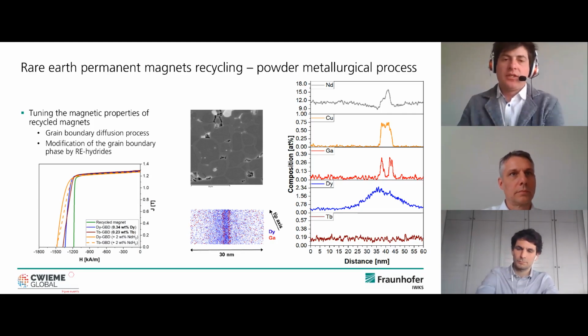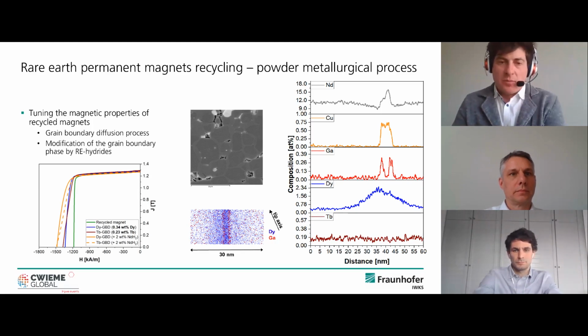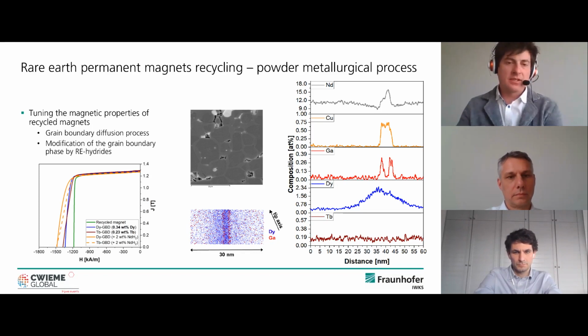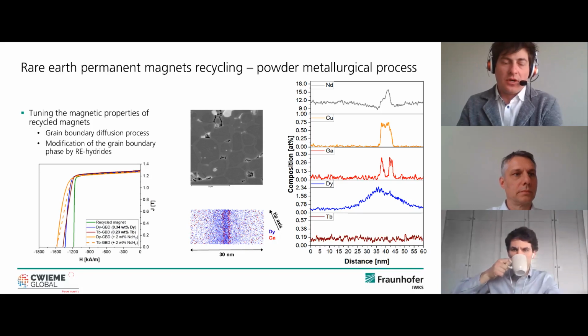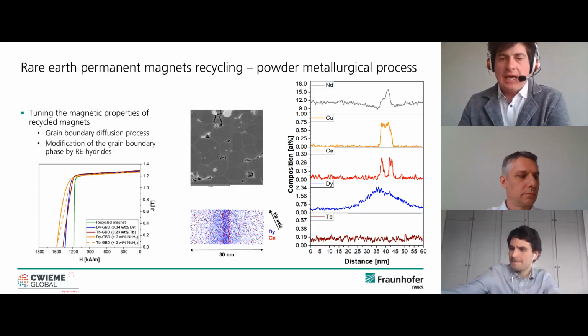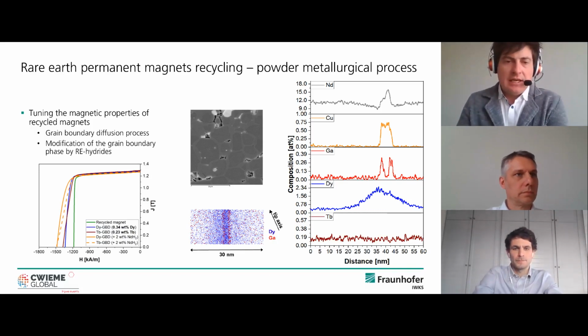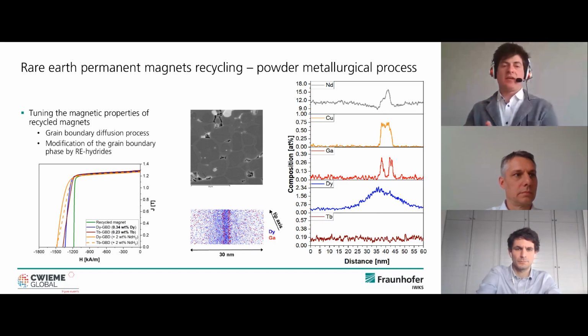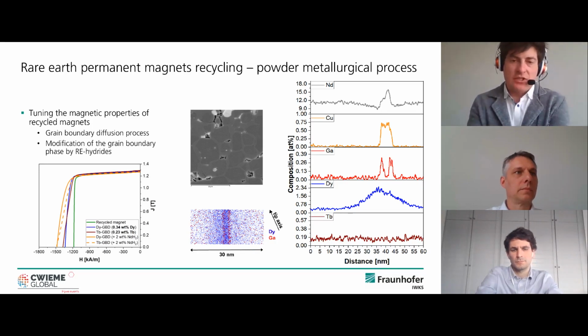Therefore, we have to magnetically harden this phase. And this can be done. The process, of course, is known from primary material production for magnets. However, it can also be used for recycling technologies. And it is shown here nicely that by combining different kinds of grain boundary modification, grain boundary diffusion processes, you can tailor the magnetic properties to meet the demand of the specification.